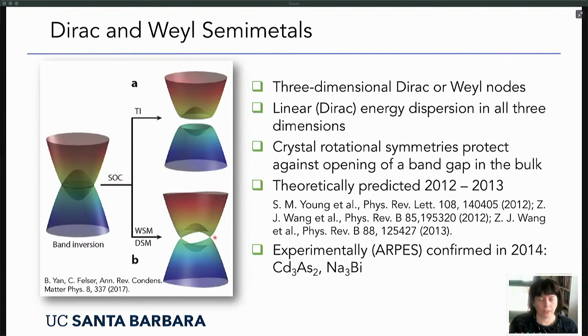So unlike graphene, they're sometimes considered to be the 3D equivalents of graphene, you have this linear energy dispersion around these nodes in all three dimensions. The important part about this is that what's often very important in these materials is certain crystalline symmetries that protect these nodes. And conversely, and this is a theme of my talk here, if you, for example, break these symmetries, in cadmium arsenide it's the fourfold rotational symmetry, you get a band gap and you get a topological insulator. Okay, and you can see where this is going with thin films.